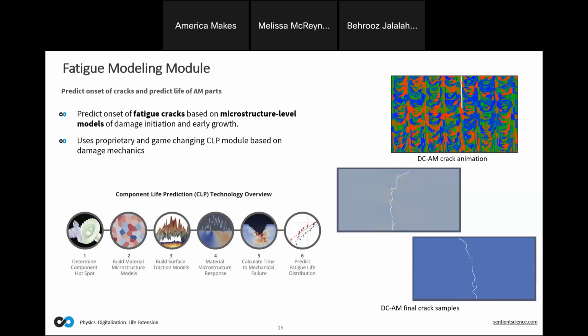And as we know, when we are talking about high cycle fatigue, in almost 90% of the cases, most of the life is spent actually in that crack initiation stage, especially if you're working with sensitive applications like aerospace. So the tool that we are providing here, the good thing is that it is providing the life for the crack initiation stage of the part.